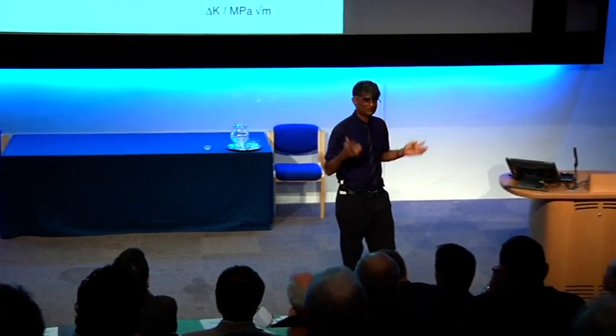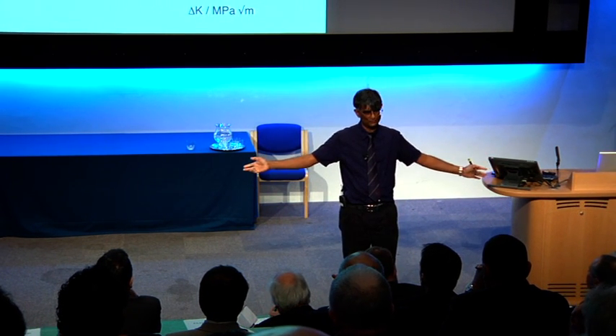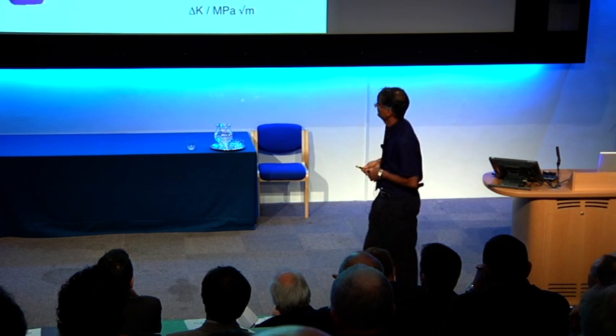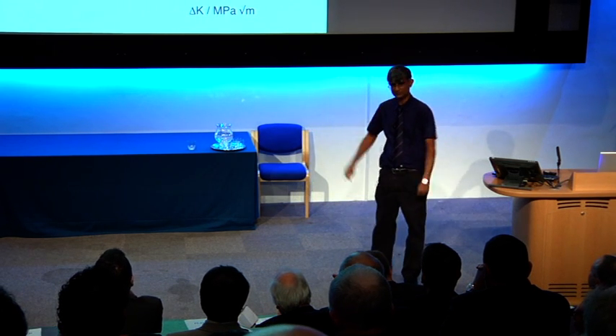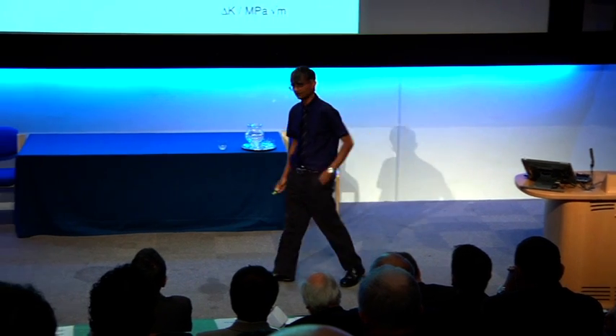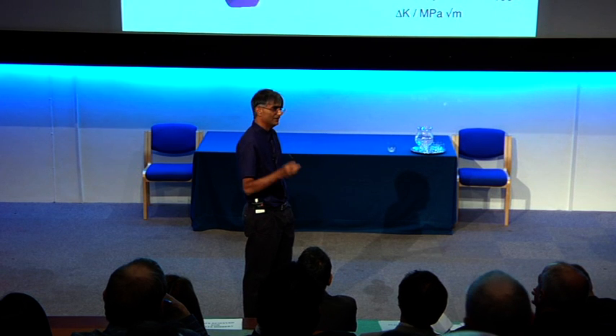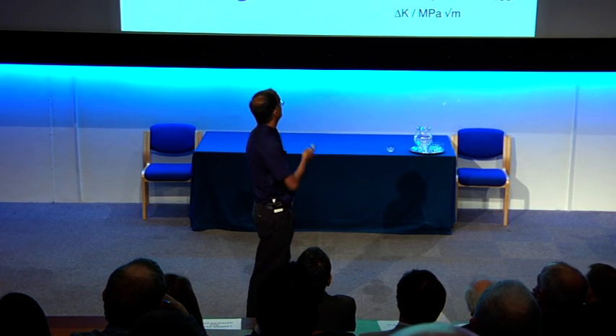So what we did is we collected catalogs of reported fatigue crack properties for a vast range of steels, nothing to do with bearing steels, okay? Because you know, steels are steels and we should be able to pull data and explain data in other systems. We made a crack prop model, and you know, this model is amazing. All you need to know is these inputs. We can even, with the same inputs, predict what happens in titanium alloys, nickel-based super alloys, and aluminum alloys without any modifications to the model.